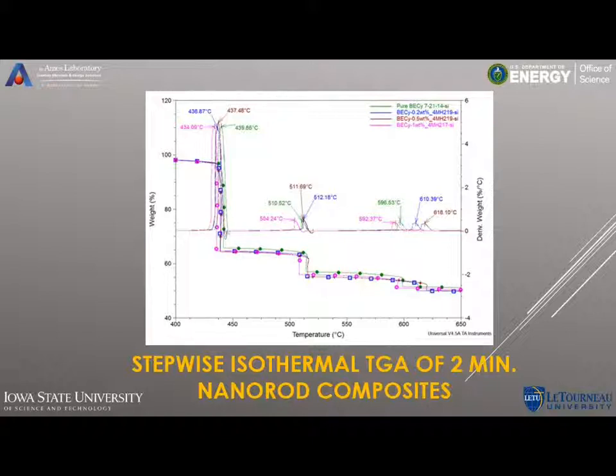Here is a different type of chart that's showing how the mass changed at different temperatures. This is isothermal, and so once the instrument detected a change of mass at a certain temperature, it held that temperature constant until the change of mass ceased. And so the sample stopped burning at that temperature. And then it went on to ramp up the temperature further until it reached another burning point. And so you can see that the sample is burning away at two different temperatures, it looks like. One at about, let's see, 448 degrees C, and then another at 511 degrees C or so. And that might be because you have two different types of polymers in this, one cross-linked and one not, and so those would have different burning points.